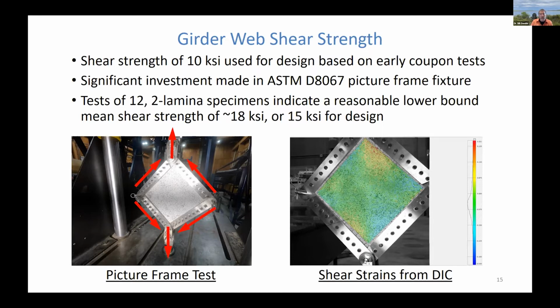To better assess shear strength, we made a pretty significant investment in an ASTM picture frame fixture. And this is a particular test, D8067, which is designed specifically to determine in-plane shear strength of foam core FRP panels. And you can see a picture frame test on the lower left. So this has 4 edges of a panel that are attached to a fixture that's fully pinned. And so we have this diamond configuration, and we put it in tension. When we put it in tension, we're inducing a state of almost pure shear stress on that specimen.